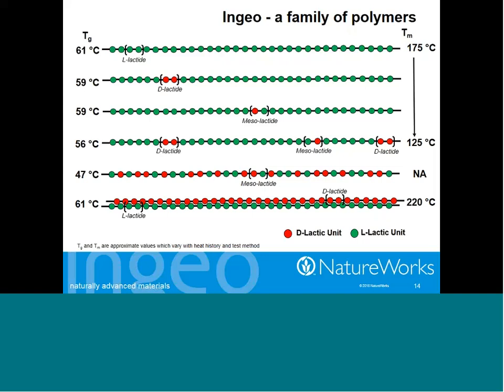And then as we start to introduce comonomers, either D-lactide, mesolactide, or mixtures of those two, we can suppress the melting point of the material, suppress the crystallization rate, and suppress the extent of crystallization. And if we make something that has a substantial amount of mesolactide or all mesolactide, using the catalyst and process that we have in Blair, we can make a truly amorphous material.